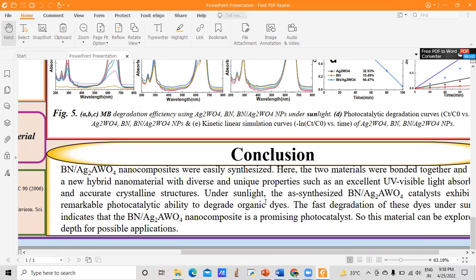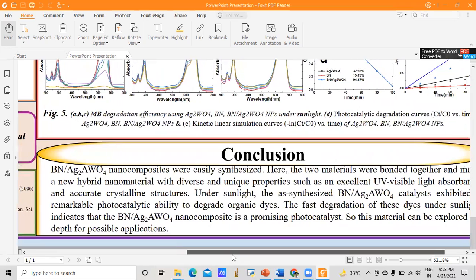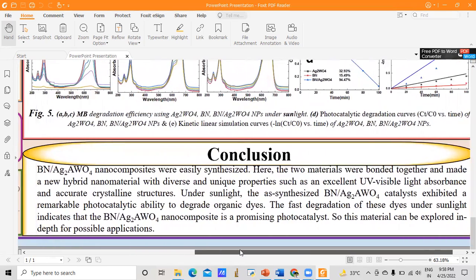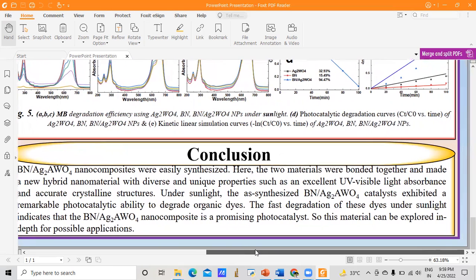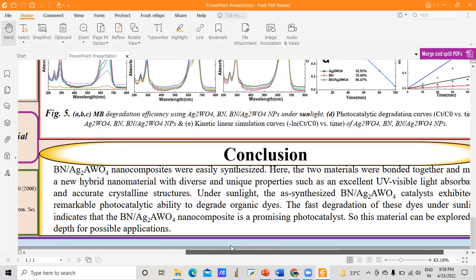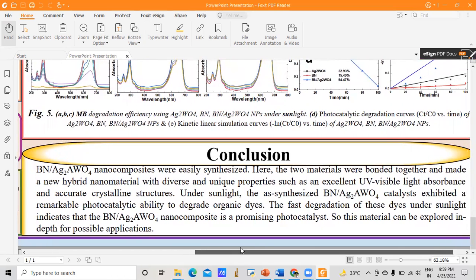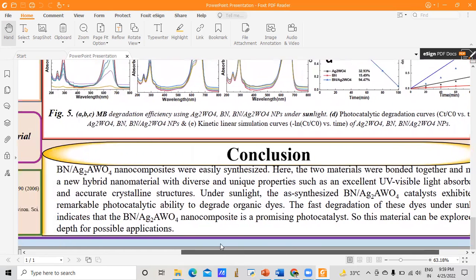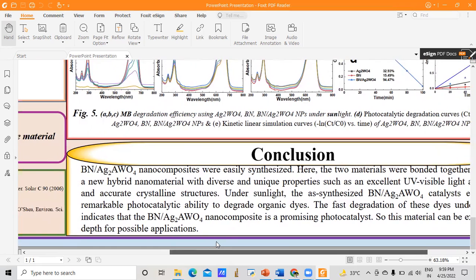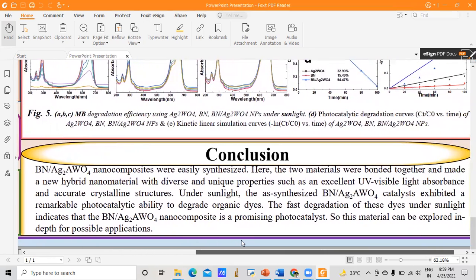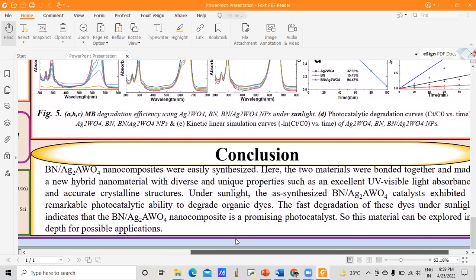So in conclusion, we can say that the BN-Ag2WO4 nanocomposites were easily synthesized. Here, the two materials were bonded together and made a new hybrid nanomaterial with diverse and unique properties such as excellent UV visible light absorbance and accurate crystalline structure. Under sunlight, the as-synthesized material exhibits a remarkable photocatalytic ability to degrade organic dye. The faster degradation of this dye under sunlight indicates that the BN-Ag2WO4 nanocomposite is a promising photocatalyst. So these materials can be explored in depth for possible applications.